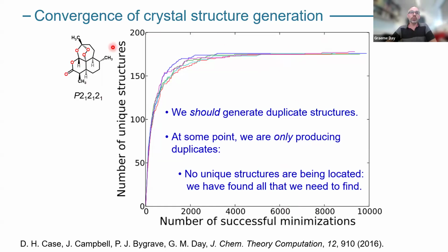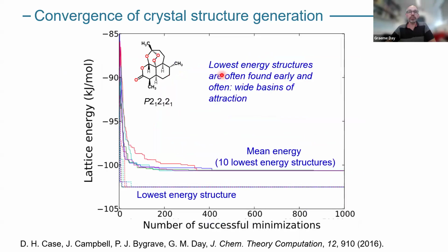But what you find is the number of unique structures is only in the hundreds. We're interested in, of course, the lowest energy structures from this search. So these dashed lines I'm showing here show the lowest energy structure I've found so far in this space group.